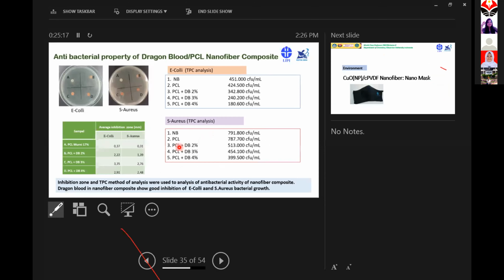Then we try to measure how effective this nanocomposite dragon blood PCL nanofiber composite is to inhibit bacteria. We measure this property using the inhibition zone and TPC method. You can see here the nanofiber composite is active to inhibit E. coli and S. aureus bacteria. It means from this result, this composite dragon blood polycaprolactone nanofiber composite is a good candidate for wound dressing application.